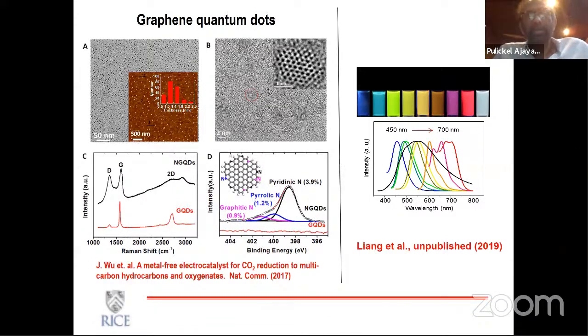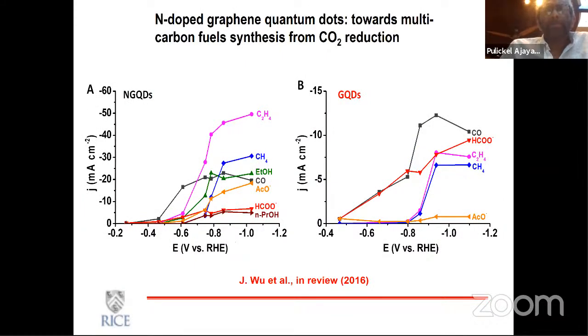And graphene, obviously, there's a lot of work on graphene. And you can these days get quite a range of optical behavior through pretty much the entire spectrum of light. You can get the colors by either doping or by changing the size of these quantum dots. So that's again a totally different field in itself, and a lot of people are working on this. Some of these quantum dots are also catalytically very active because they have a large number of edge atoms, and again, if you dope them, that's even more interesting.